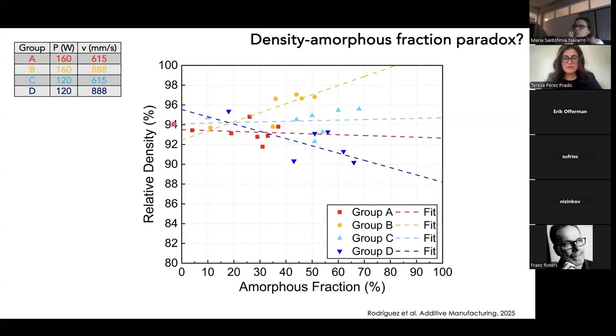And here we have some interesting data. So this is density versus amorphous fraction. And you see, for example, for group B, that we are able to reverse this trend. So in this case, both the density and the amorphous fraction, when using time delays, we can make them both vary in the same way, in the same direction, with our processing parameters.